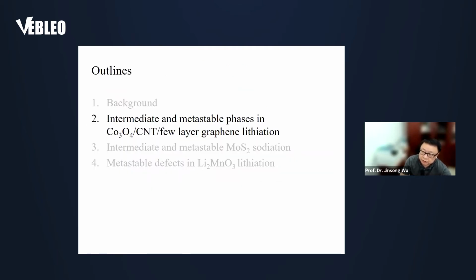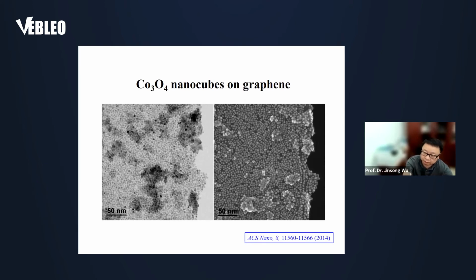All right, so the first story, or the first result that I want to show you, is lithiation of cobalt oxide, Co3O4. And here's a sample that we prepared. We prepared very fine, very small Co3O4 nanocubes. The average length of these nanocubes is about 5 nanometers. And we grew those small nanocubes on top of few-layer graphene. And you see here's the few-layer graphene, and it is decorated with a lot of nanocubes. And this is the first sample that we used.